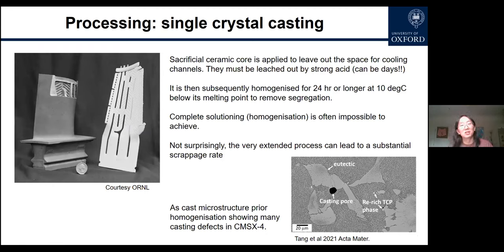Once you have your material leached out, it's going to be heat treated, or let's say a homogenization treatment, usually just a few degrees or 10 or 20 degrees below its incipient melting point, to remove any segregation and to achieve the properties. So it is not a surprise at all that this very long process can lead to a very substantial scrap rate. In the past, I think this was around 10% success rate, and then it increased to around 30%, 70%. And I think I've read some reports recently that a good casting house can achieve roughly 95% or even higher success rate. But these are still very, very difficult processes.